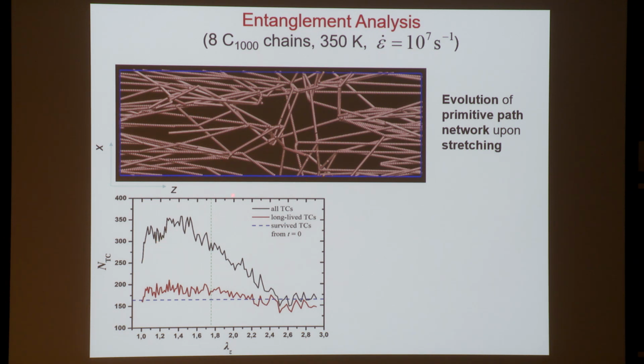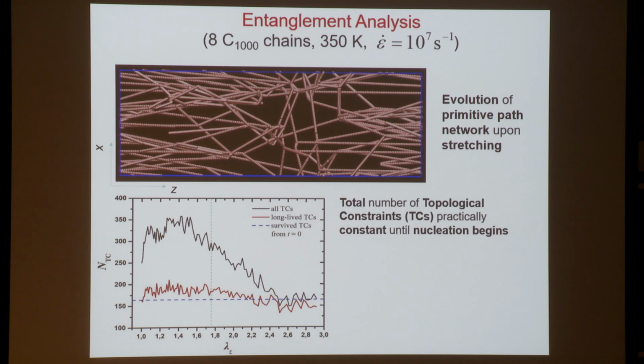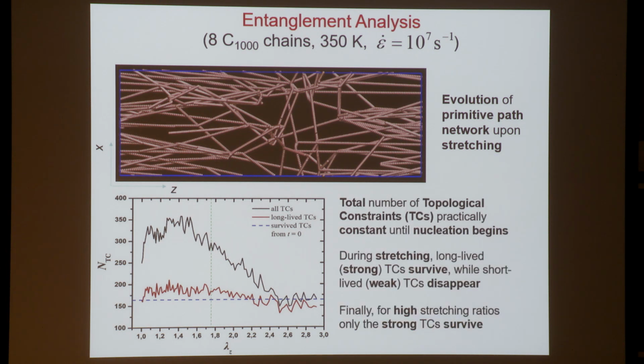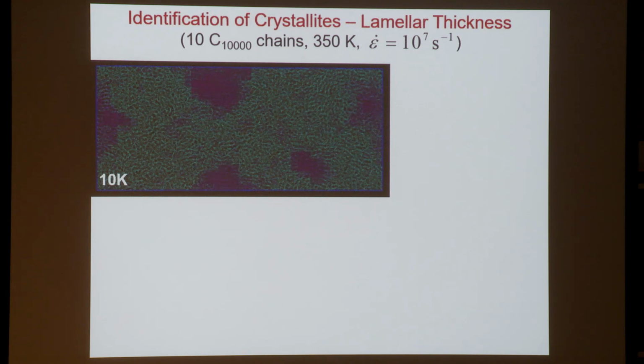And what this seems to indicate is that the total number of entanglements goes down. The long-lived entanglements go down by just a little bit. And in the end, in the semicrystalline film, one has only long-lived entanglements, which have populated this middle amorphous region in the film. So one can even try to estimate the crystallite size, or the lamellar size, in these ordered materials.